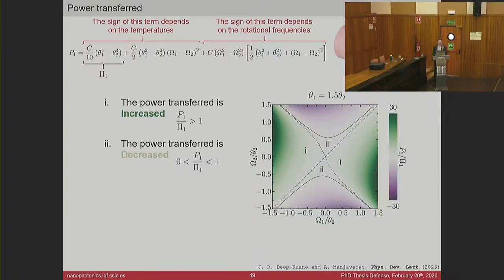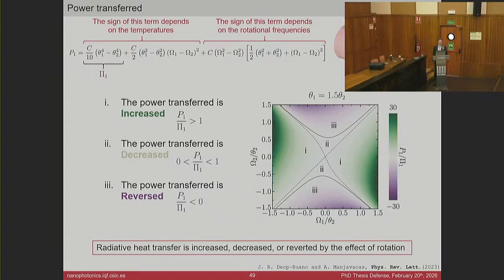And when this term here is not only negative but becomes larger in magnitude, then the power transfer is reversed. In such a case, the power transfer will be from the cold nanostructure to the hot one. So we can see that depending on the parameters of the system, we can have a lot of flexibility and a really rich behavior in the radiated heat transfer.